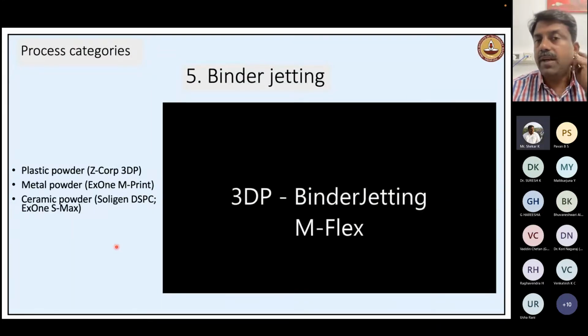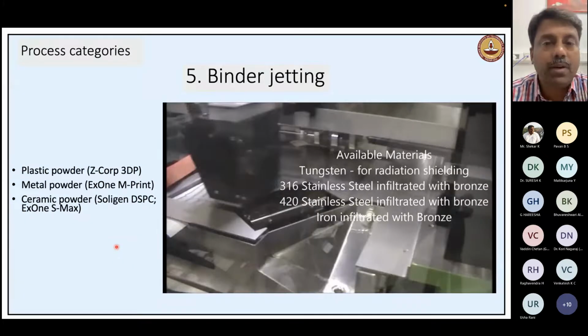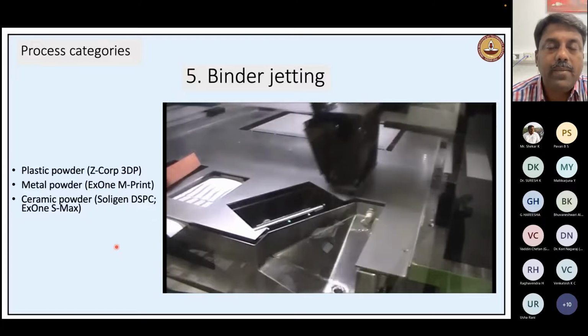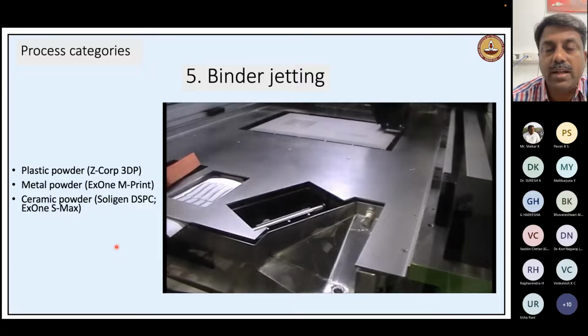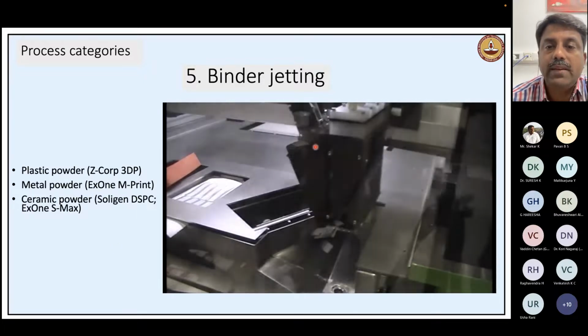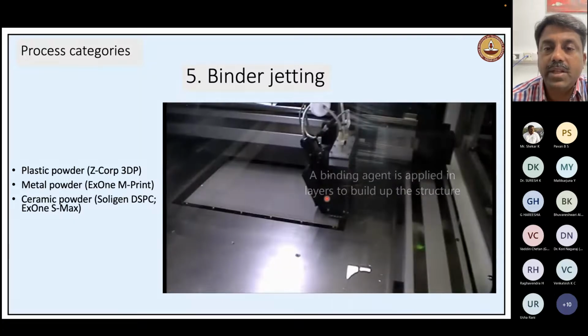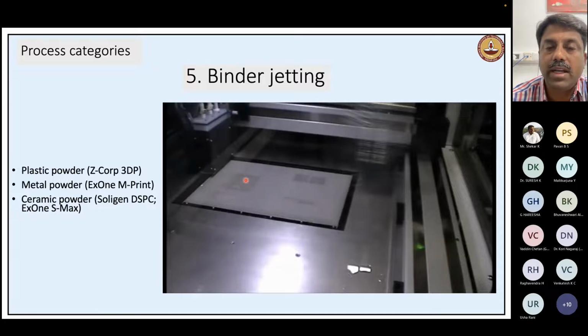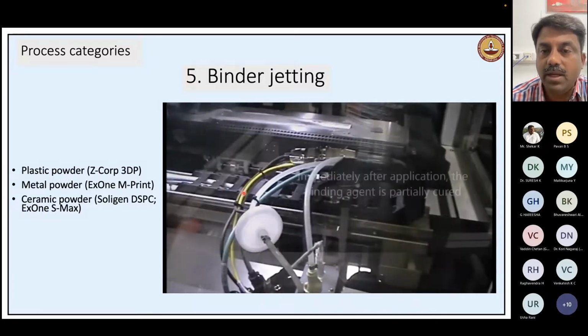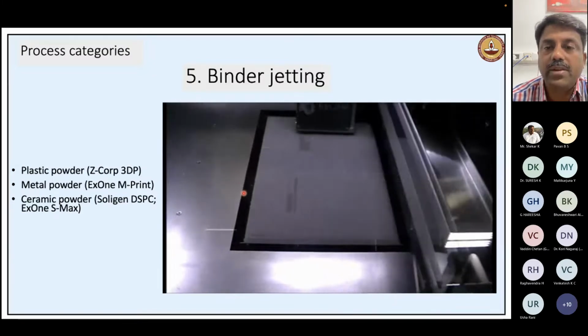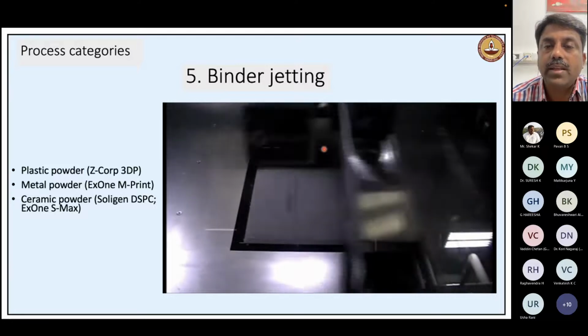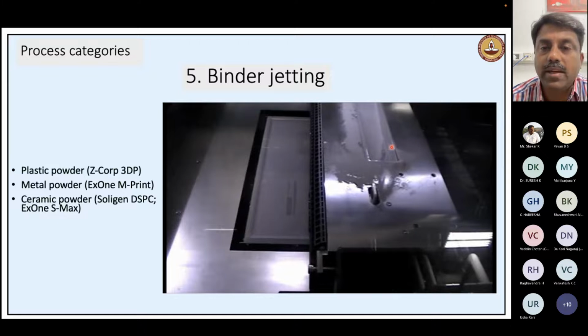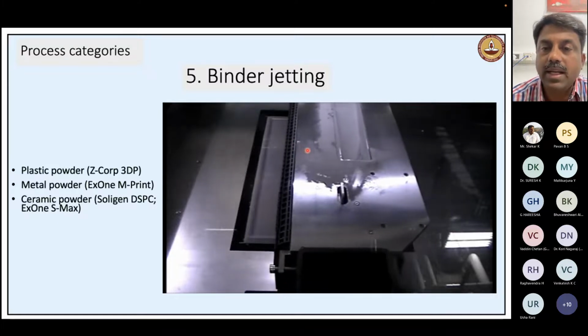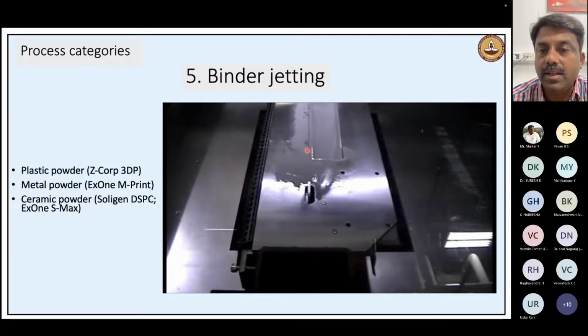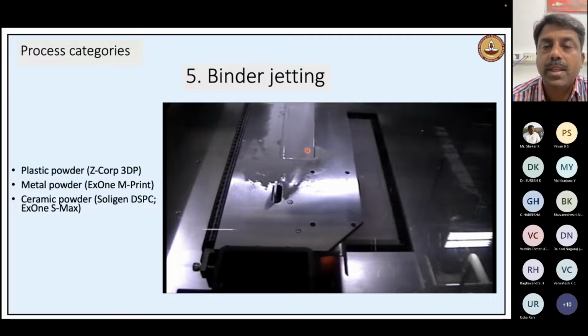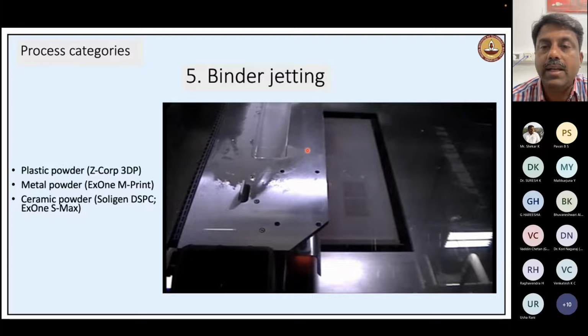The fifth technique which is available is binder jetting. In binder jetting, it is similar to a powder bed, but here the powder is not molten or sintered by a heat source. We selectively eject the binding agent onto a location where we want to create a consolidation. So binders are added only at the location where we want consolidation. Then subsequently we can let a small heater heat up the locations where binder is added, and the binder reacts with the powder, and then the powder gets consolidated to create a solid object. Here we are not melting the powder.